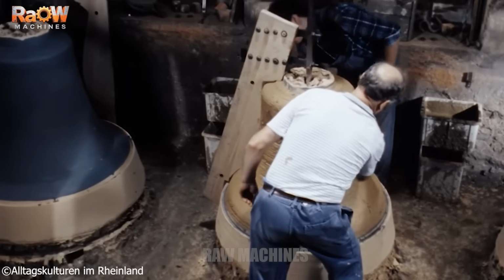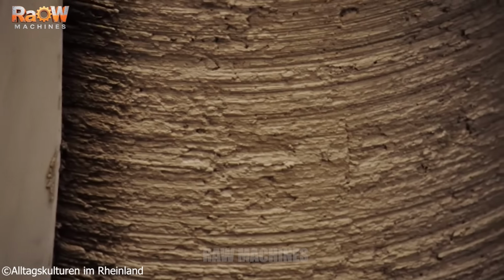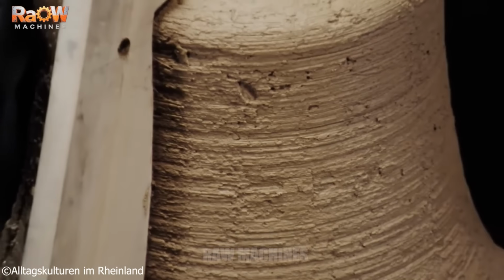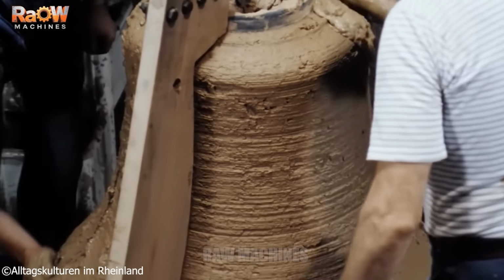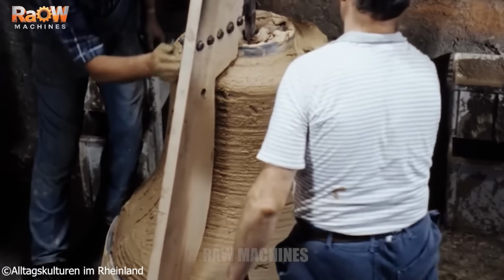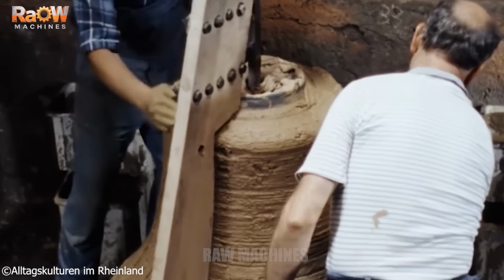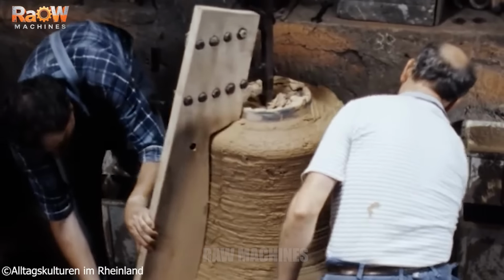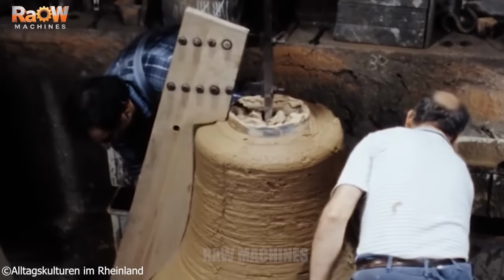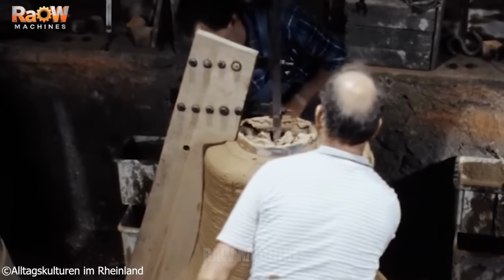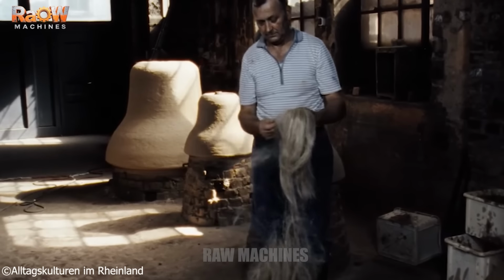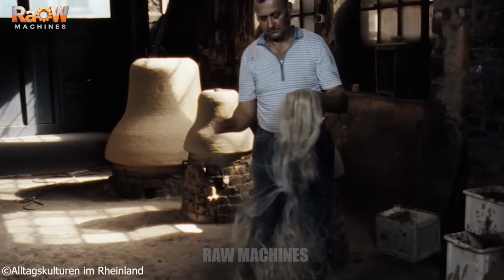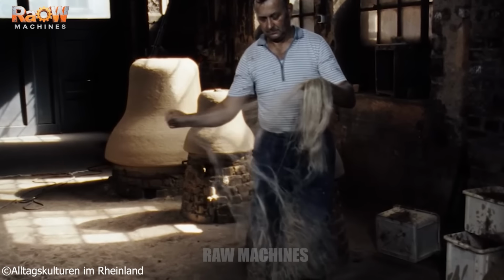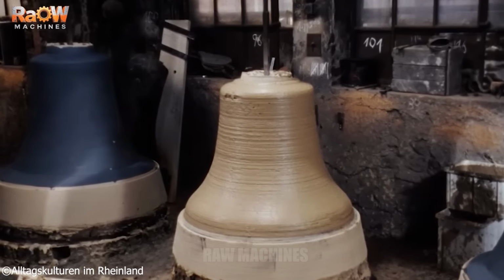The clay mixture used for the false bell is blended with fermented horse manure, which acts as a plasticizer and improves fineness. The manure comes from draft horses, fed exclusively on hay and oats, and is aged together with the clay for several months to achieve the required plasticity. As suitable manure sources have become increasingly scarce, the foundry maintains its own horses to ensure a consistent supply of this material.